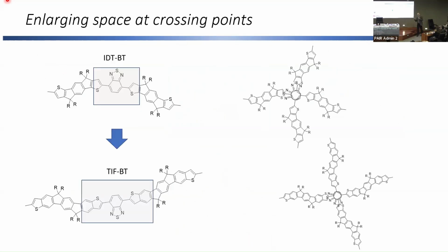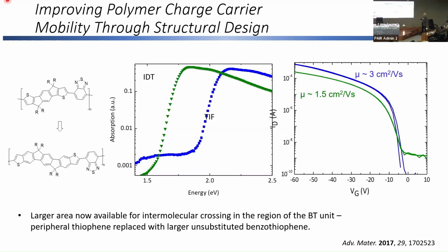So if the side chains push the contacts to the part of the backbone where there is no side chain, in other words, the BT part of this polymer, if we gave it more room, in other words, pushing the side chains further apart and introducing more free volume here, would that help facilitate these contacts, make them easier to find, and improve the transport properties? So we tried that, and in fact it did work.